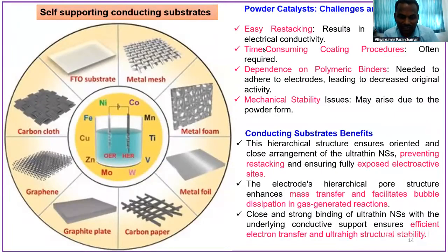Once we decide the synthesis method, then what kind of material do we need, like powder material or grown on some substrates? Why do we focus on substrates like FTO, nickel foam, copper foam, graphene substrate, metal mesh, carbon cloth? Because powder material easily restacks, it needs polymer binders to stick with the working electrodes, as well as for mechanical stability during operation. Once the current or potential is applied, the material peels off the glassy carbon electrode. So if you directly grow the material on substrates, like nickel foam or FTO, whatever substrate you use.